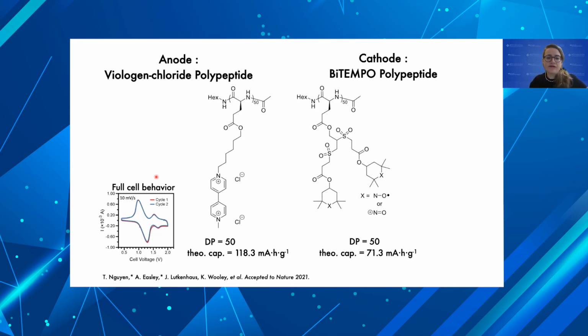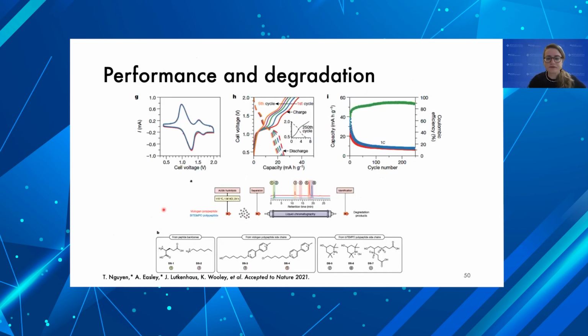We assembled them into a full cell. So you can see redox peaks here attributed to the full cell. And we've tested their performance. We can achieve about 80% of the full cell capacity in the initial cycles, but with increased cycling, we do see degradation. Again, this is associated with dissolution, which is a common issue for redox-active polymer batteries. So we can potentially solve this issue by cross-linking the polymer or designing polymers that don't dissolve in the electrolyte.